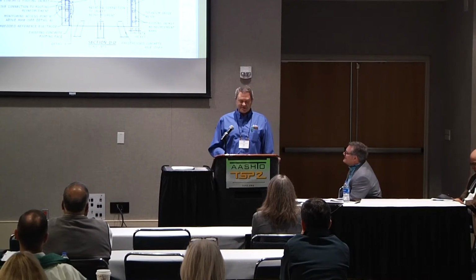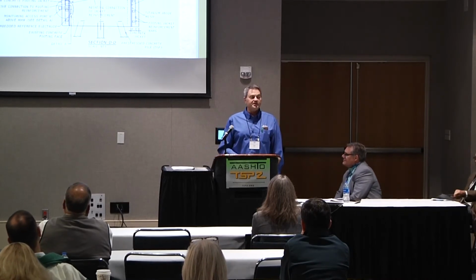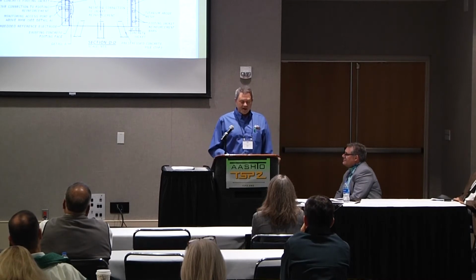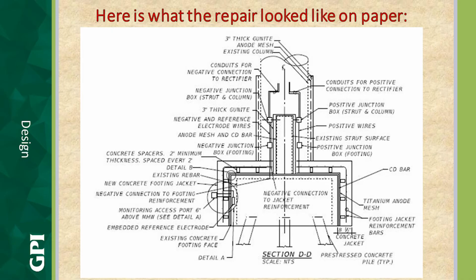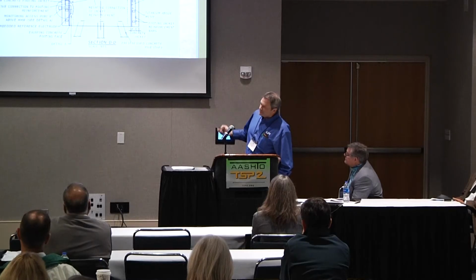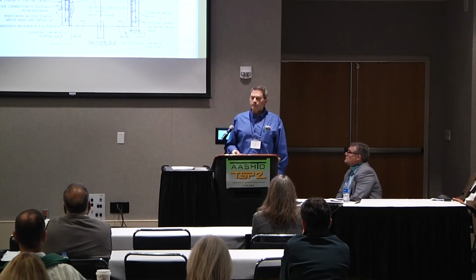FDOT rehabilitated these elements by removing the bad concrete, installing additional reinforcement, installing a CP system, and then encasing it with new concrete. And this is what the design drawing looked like. We've got conduits, we've got our negative junction box, we've got a 3-inch gunite layer, we've got negative and reference electrode wires, here's our anode mesh and our current distribution bar, our negative junction box, we've got our concrete spacers, our new concrete footing jacket, we've got our negative connections to the footing reinforcement, we've got access ports, our embedded reference electrodes right here, and so on. We won't go through the whole drawing, but this is what the design for the repair of that footer looked like.